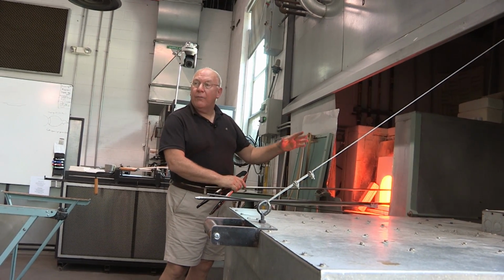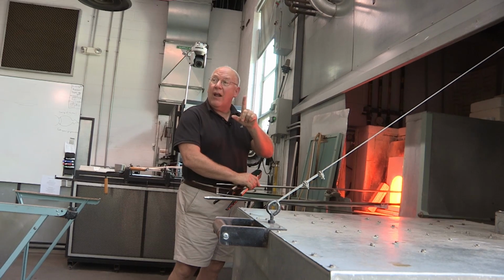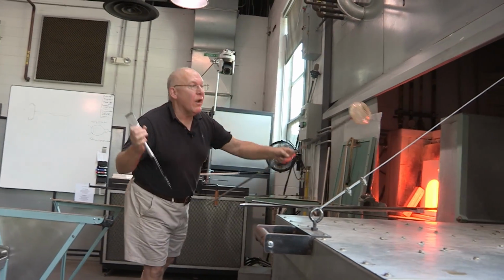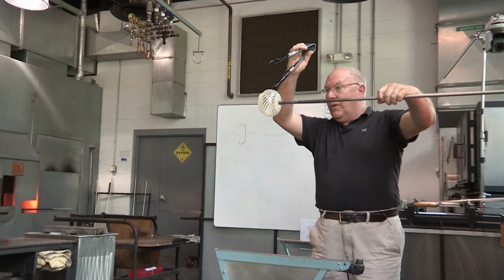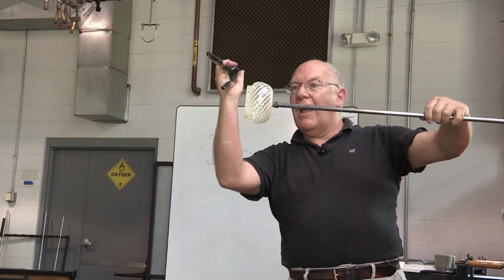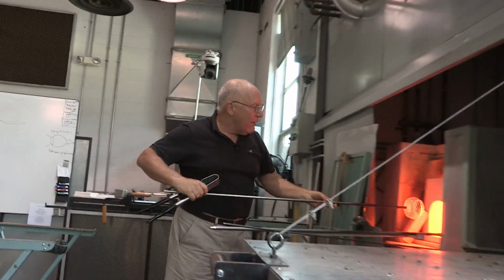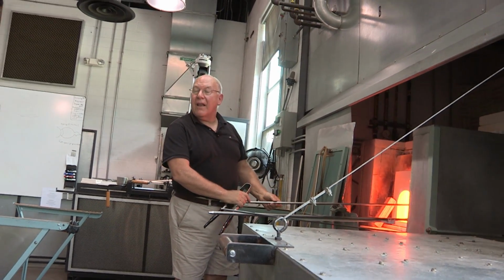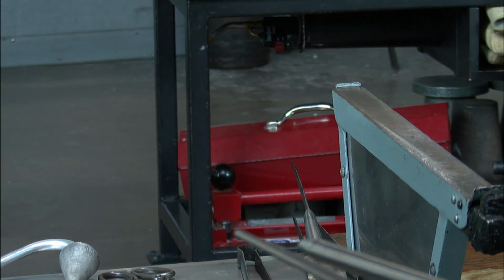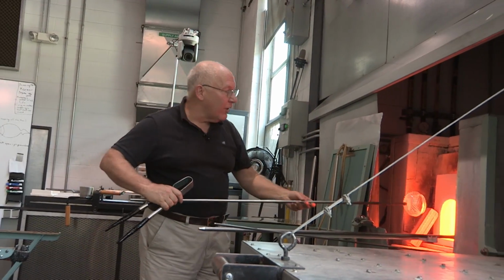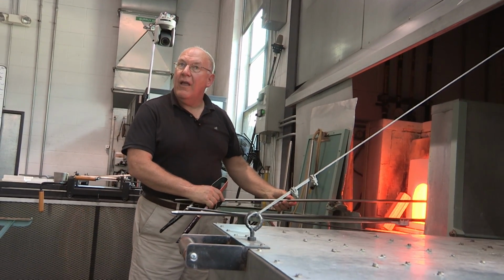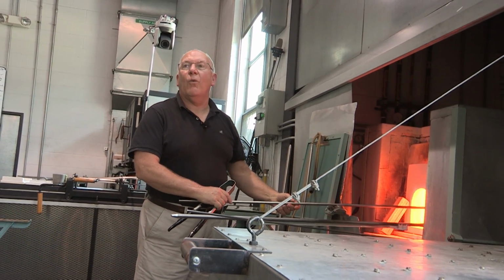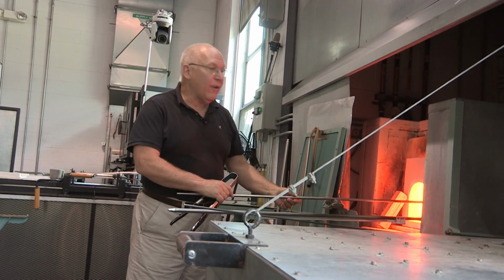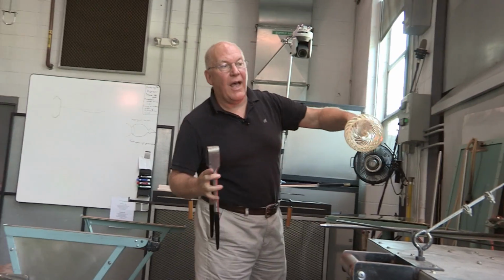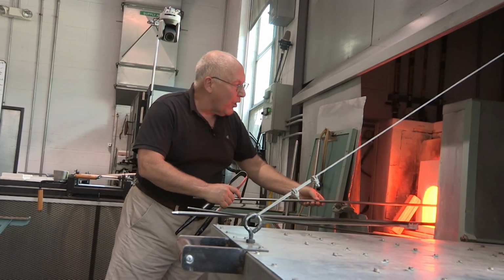Most of the work I've been doing now has been on the rim, so the rim is hot. But the part I want to shape right now isn't. What I want to shape is way down here. This is all soft. To get this hot without overheating that, I'm going to use what I call the heat treatment. I'm going to heat for maybe 5-6 seconds deep in the furnace, come out, let the edge, which is real hot, cool off a little bit, and I'll do that 3 or 4 times. And that's a really good way to get everything soft without overheating the thinnest and the hottest parts. Do that one more time and then do the base broadening move.